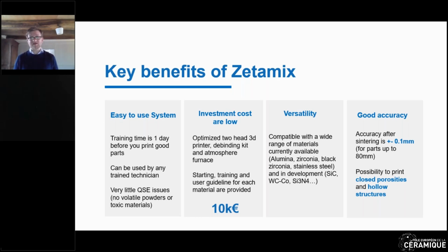It's also a versatile technology. It is compatible with a wide range of materials. For the moment, what is available is alumina, zirconia, black zirconia, and stainless steel, but potentially any material that can be sintered could be printed by that technology. We have a lot of developments going on silicon carbide, tungsten carbide, silicon nitride. I saw someone mention fused silicate could be done also, even though it's not there yet, and some other metal. So that's really a technology that is compatible with a lot of materials.